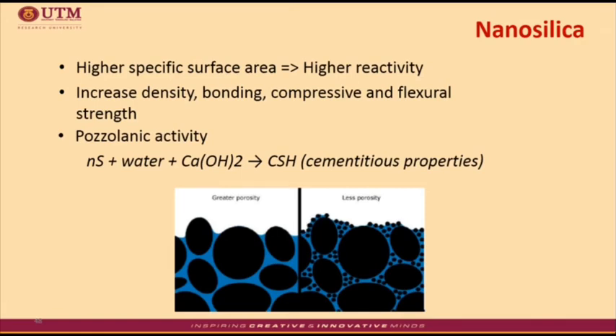The compressive strength evaluation of cement mortar with nanosilica was discussed for different water-cement ratio, and from the experimental results, it is confirmed that the compressive strength of mortars with nanosilica were higher than conventional at 7 and 28 days. It was found that the nanosilica behaves not only as a filler to improve the microstructure, but also as an activator to promote pozzolanic reactions and superplasticizer that plays an important role during mixing the cement with nanoparticles.